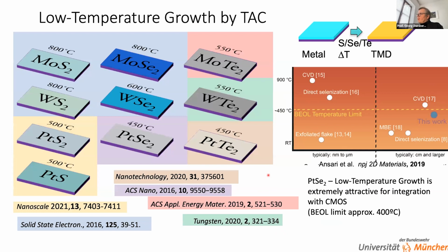The one thing we noticed looking at those materials is this procedure of converting a very thin metal layer, which is a perfectly scalable process because we essentially can do this on wafers quite nicely. You just need a good sputter or evaporation tool. Some of those materials, in particular platinum diselenide, can be synthesized at relatively low temperatures.